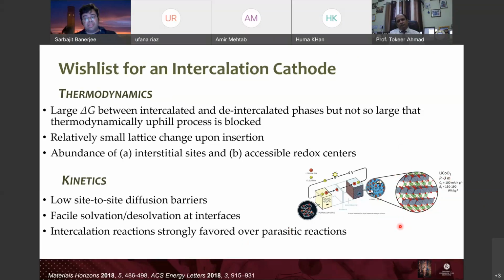For instance, in the case of this system, could be the lithium reacting with oxygen to form lithium oxide and some sort of cobalt suboxide, right? So this is a problem because once that reaction happens, it's going to be very difficult to get that to reverse, and then you've lost that capacity, right? Because you're not going to get that cobalt back. It's going to stay in its reduced form, and then you're sort of stuck. So this is a very important point, that these insertion reactions must be very strongly favored over parasitic reactions.